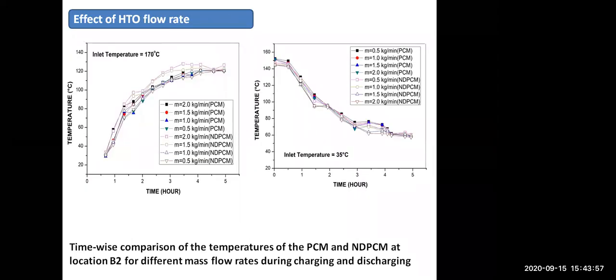Then the effect of heat transfer fluid. It's a heat transfer oil. That's the term we are using in our research, but commonly it's called heat transfer fluid. The melting time was decreased by 20% for PCM and 30% for NDPCM when the flow rate increased from 0.5 to 2 kilogram per minute. Then solidification time was reduced by 19% for PCM and 20% for NDPCM when the flow rate increased from 0.5 to 2 kg per minute.